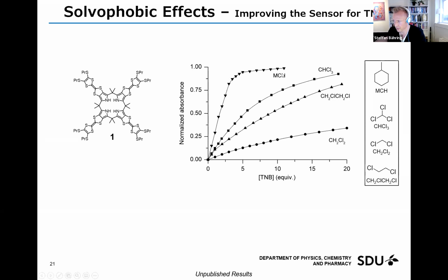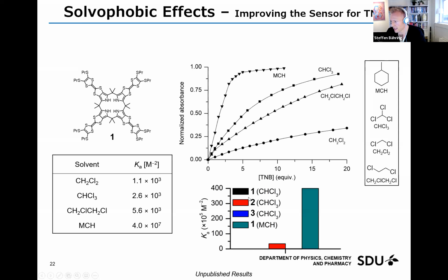Chloroform is also a better solvent, but we tried to dissolve it in methylcyclohexane, which is a solvent that we didn't think would be as good. So you can see that it's a very apolar solvent, but the calix[4]pyrrole was actually quite soluble in this solvent, and you can see that already by just introducing a few equivalents of the TNB molecule, it becomes completely saturated. So you can see here in the overall binding constants that we're able to reach 10 to the 7th when we use methylcyclohexane. So just changing the solvent would actually work in improving the sensor capabilities.